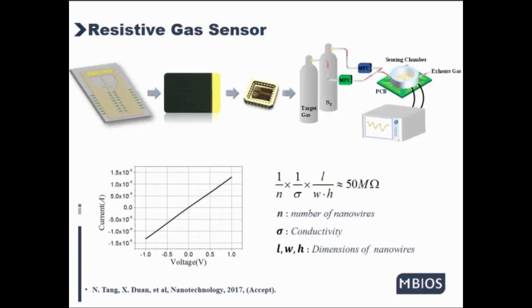Okay, after the formation of the nanowires, the metal electrodes were formed on the side of the nanowires with thermal evaporation through a shadow mask. After that, the whole substrate was sealed into a package, and the metal electrodes were well bonded to the connector. Thus, a fully resistive gas sensor is successfully fabricated. And the current-voltage results clearly show that the resistive gas sensor has a good ohmic property.